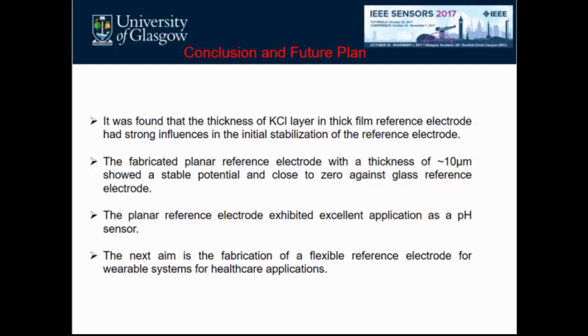As a next step, now we are fabricating a flexible reference electrode based on a PET substrate, and in that case, here I used cellulose as a binder, and in the next flexible one I used a room temperature curable binder paste.